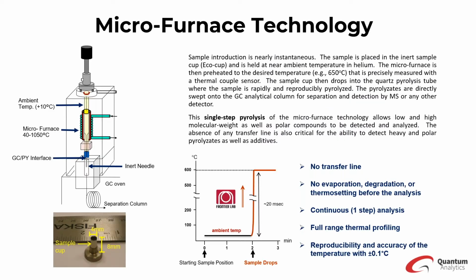So here's a little cross-section of your microfurnace. This furnace houses a quartz tube. This is where the sample cup is dropped into to be pyrolyzed by the furnace. The sample cup pictured here only requires microgram amounts of your sample, as is cut, scraped, punctured, or whatever have you from your polymer. And once pyrolysis begins, all of the pyrolysates, or the products of your thermal sampling, are swept right into the inlet to be separated and analyzed by the column detector.